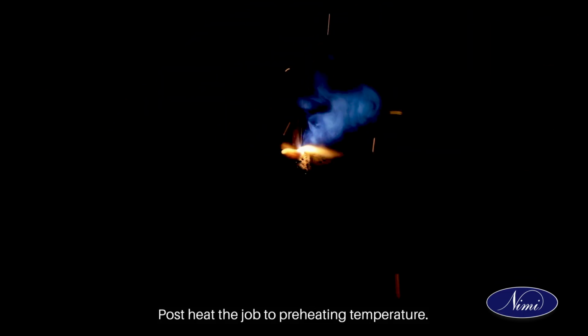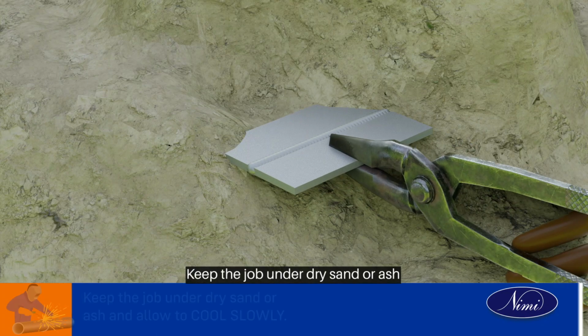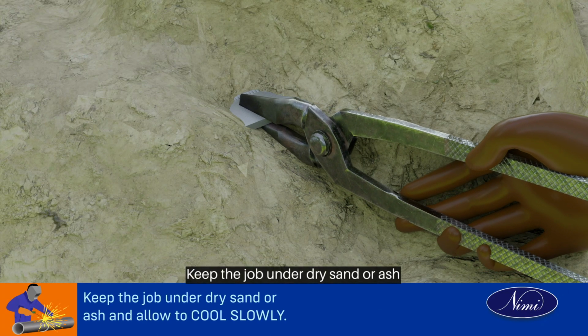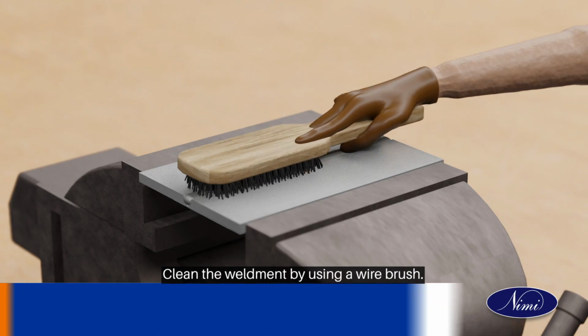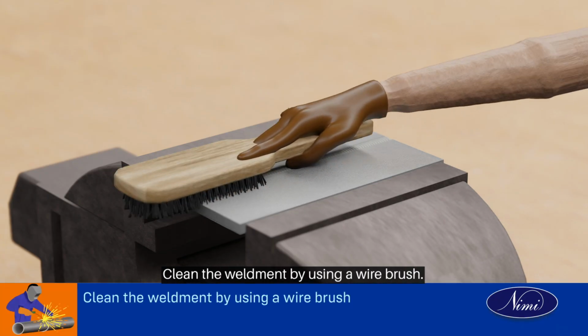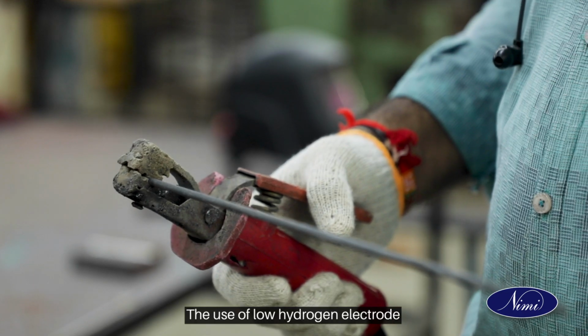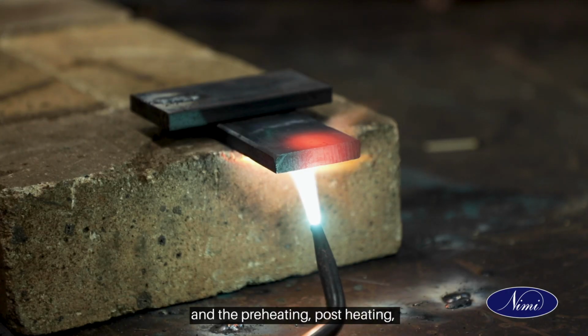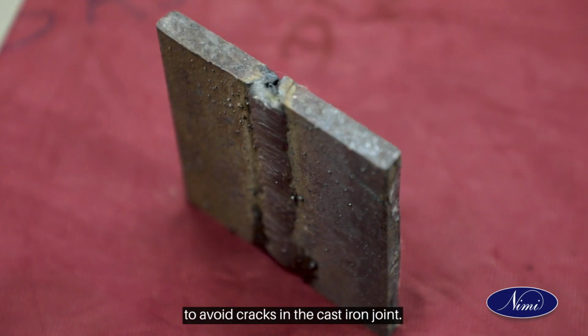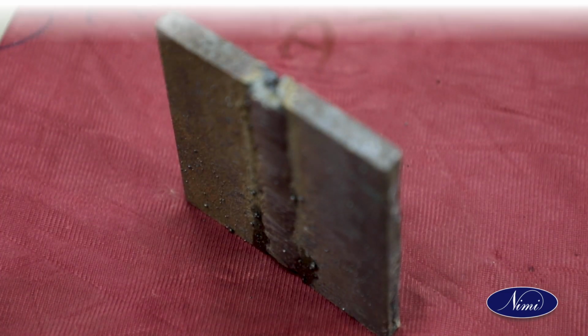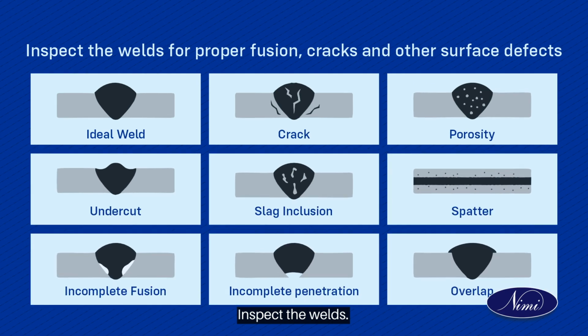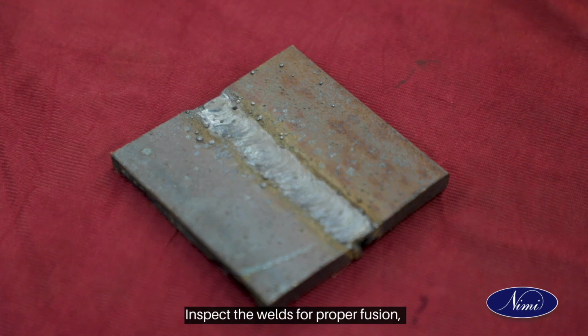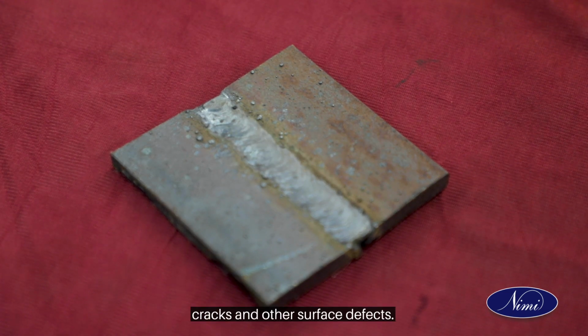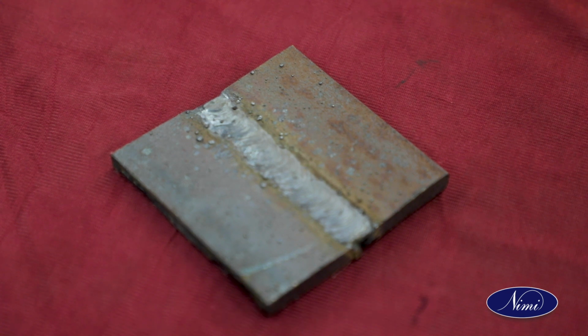Post-heat the job to preheating temperature. Keep the job under dry sand or ash and allow to cool slowly. Clean the weldment by using a wire brush. The use of low hydrogen electrode and the preheating, post-heating, peening, and slow cooling are essential to avoid cracks in the cast iron joint. Inspect the welds. Inspect the welds for proper fusion, cracks, and other surface defects.